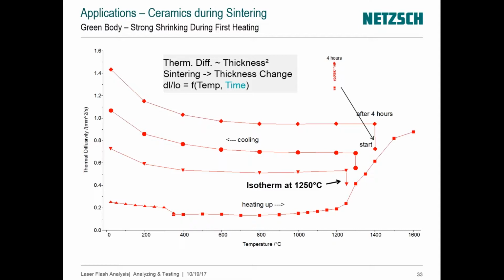It's very important for subsequent process control to know at what temperature you should keep your specimen and for how long, to make sure that sintering really occurs and that you obtain the highest possible diffusivity, if this is your intention. So if you compare what we obtained with the diamond mark to what was obtained with the triangle mark, you can see how significantly higher the resulting diffusivity is. This is a statement for the temperature of sintering, temperature and time: how long you keep it at high elevated temperature and how high this temperature is. It's a very important criterion. This is expected for sure, but we are just documenting it.